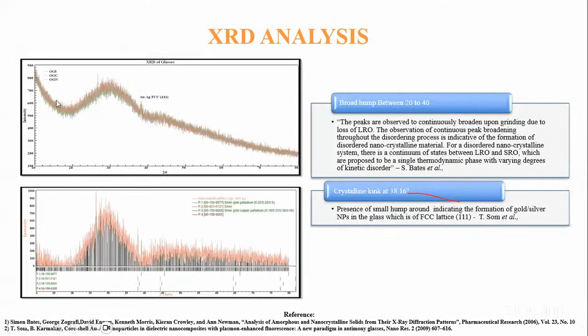So when you look at XRD, what normally happens is you see a very broad hump that is present here, and there is a small kink that you try to see at around 38.16 degree. Normally this doesn't appear in a pure glass, but if it is doped with some nanoparticles, you can confirm its presence by this. So this is one of my works where I have shown the existence of gold and silver coagulated nanoparticles in the lithium, strontium, zinc borate glasses. Okay.